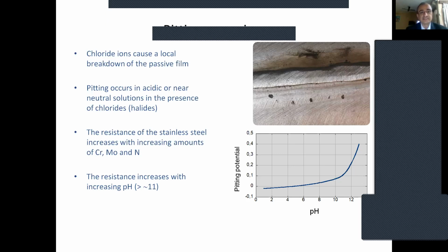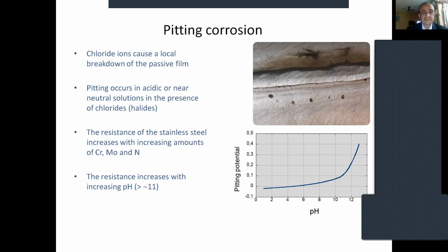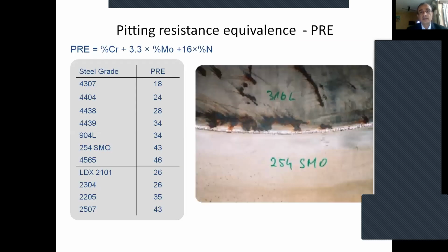Pitting occurs in acidic or near neutral solution in the presence of chloride halide. The resistance of the stainless steel increases with the increasing amount of chromium, moly and nitrogen. Chromium, moly and nitrogen are elements in the stainless steel. There are different kinds of stainless steel, which I will be covering in the future if I get the chance. The resistance increases with increasing pH value greater than 11.